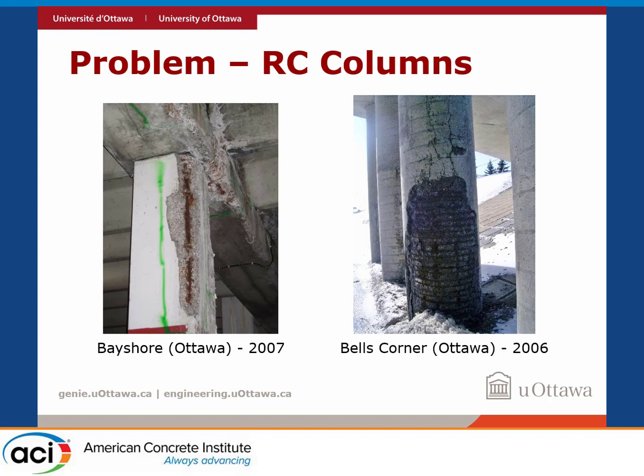Bridge piers tend to deteriorate on the side that is exposed to the traffic, and usually the area of deterioration is the splash region where the cars pass by and splash water that is laden with de-icing salts. And in this case, the entire concrete cover has delaminated, and of course, once the reinforcement is exposed, the corrosion process proceeds at a much faster rate.